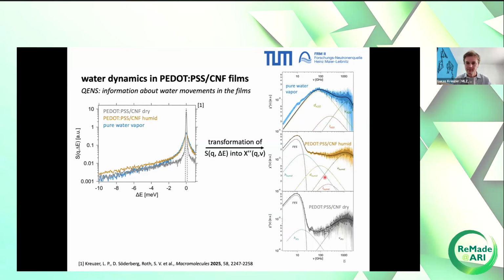If we now dry the film, some of the peaks disappear. We don't see the diffusion of this bulk water kind anymore, and this local effect is also disappearing, or at least becomes so small that we would not need to model this curve anymore. And we are left with the diffusion of hydration water and still these vibrations. So now, to us, this means that when you dry the film, bulk water is completely removed from the film. All of the bulk water is pushed out, but there's still water left in the film. But this is present as hydration water close to the polymer chains, but to a smaller part. So the amplitude of this peak decreases when you dry the film.